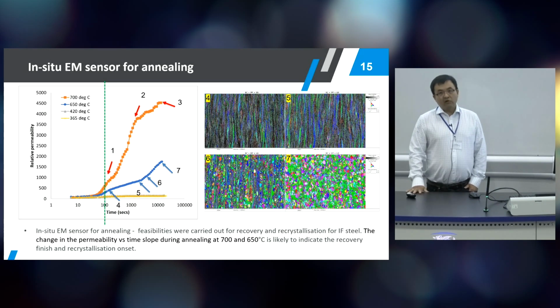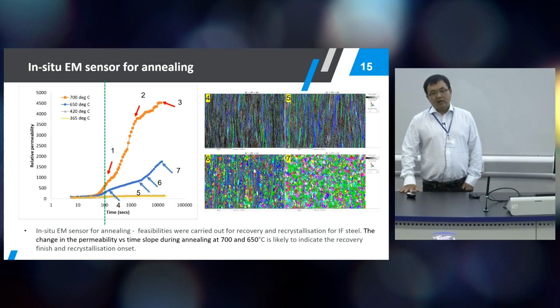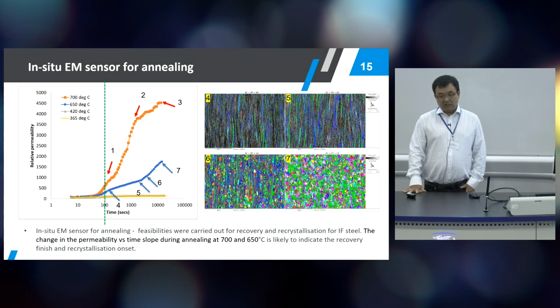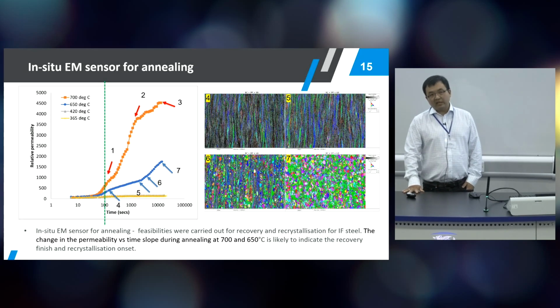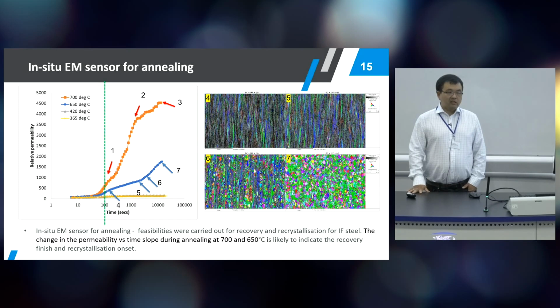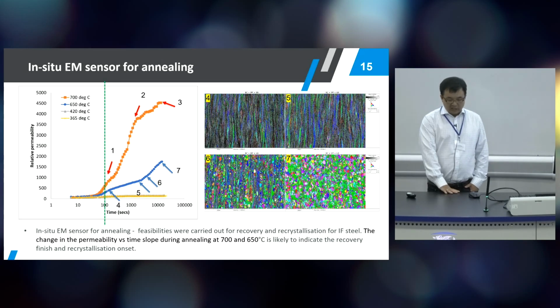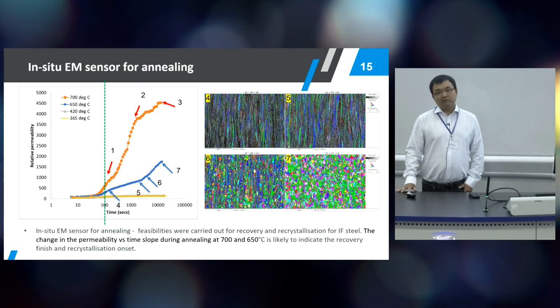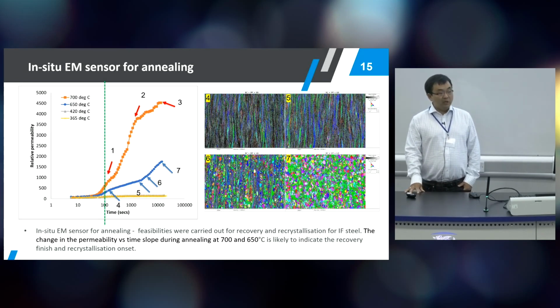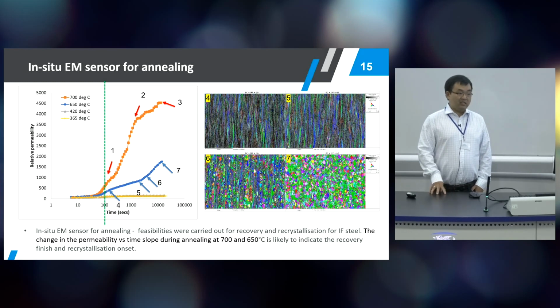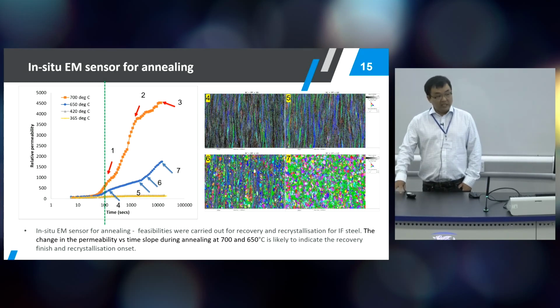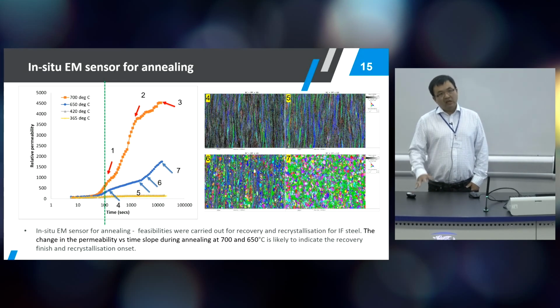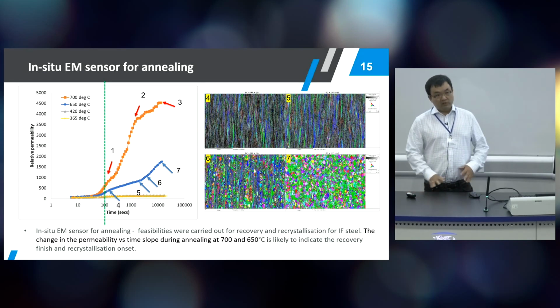So a lot of that is focused on phase transformation, and another area that we have done some feasibility work in, and which we also believe is a great sensor application area, is to apply the electromagnetic sensor technology to annealing. In this case, we have an interstitial-free grade, where we have cold rolling followed by annealing, during which recovery and recrystallization are going to happen. There we have also measured in situ the steel recovery and recrystallization process in a furnace, where a steel sample is positioned within a sensor tube. But it's the starting point of thinking, can we also apply that sensor technology to the annealing process?